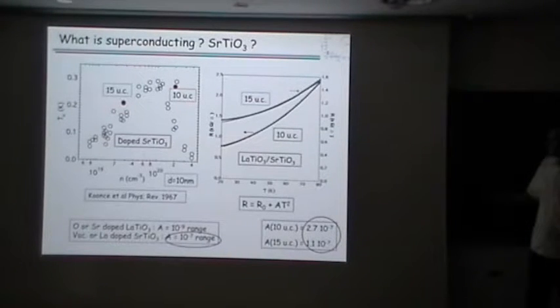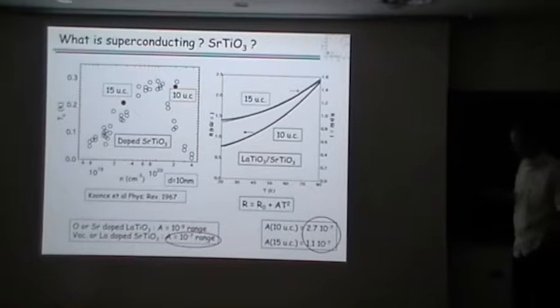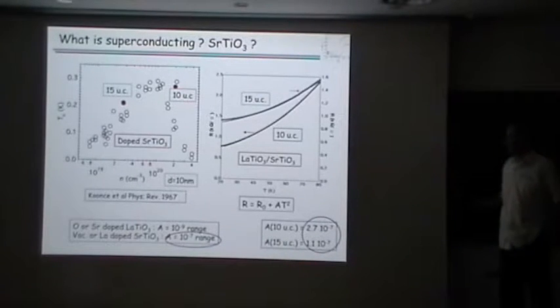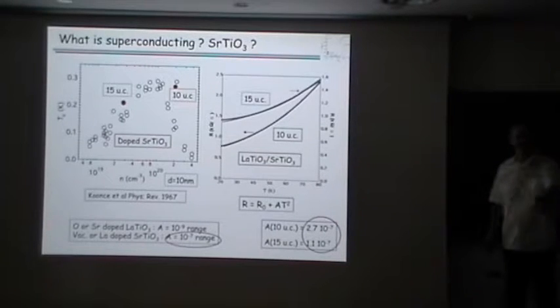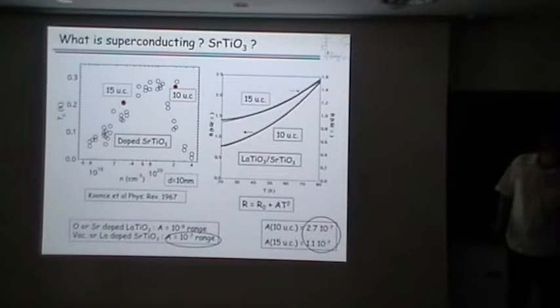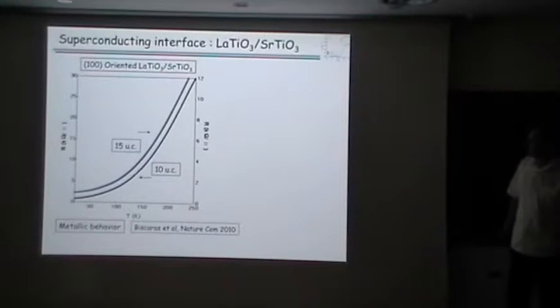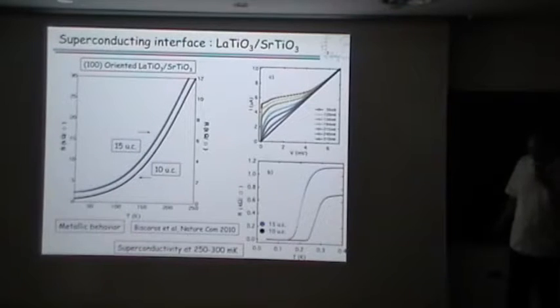And also, if you put the data we have, I mean the TCs of at least these two samples, on the plot I was showing you yesterday of the TC for bulk materials as a function of the doping. This is the log scale right now. Roughly, you are in the same range. Again, there is a lot of dispersion at this point, even in the original curve. So what you can say is that probably the electron sits in this strontium titanate, and what you see is basically the behavior of something within strontium titanate.